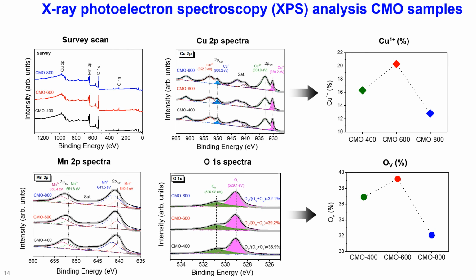Which clears that the more number of oxygen vacancies produce the electrons. So these electrons reduce the Cu2+ to Cu1+. Also, these oxygen vacancies improve and promote the electrical conductivity of the sample, which is one of the most important reasons for the higher activity of CMO 600 compared to other CMO.